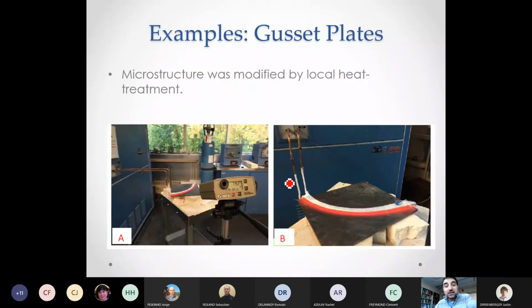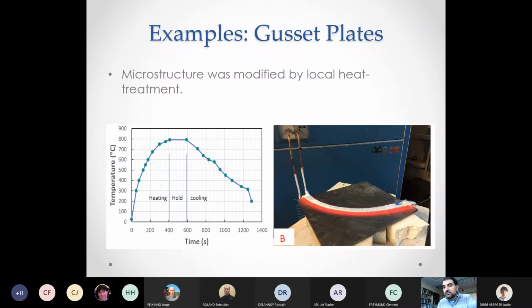In this case, we did not change the composition, we only changed the heat treatment. So we created these induction coils that allowed us to heat the material along the arc that they designed. And by choosing the temperature and the cooling rate, we were able to create a softer region in the middle of the plate, similar to the one that they had in the design.